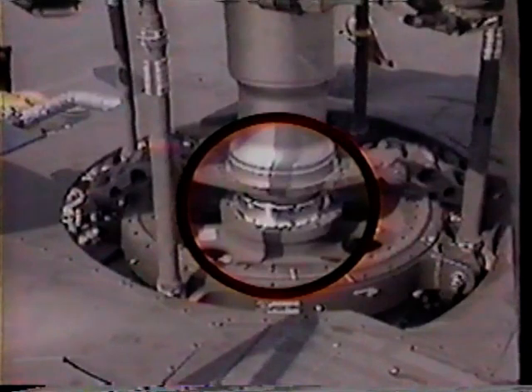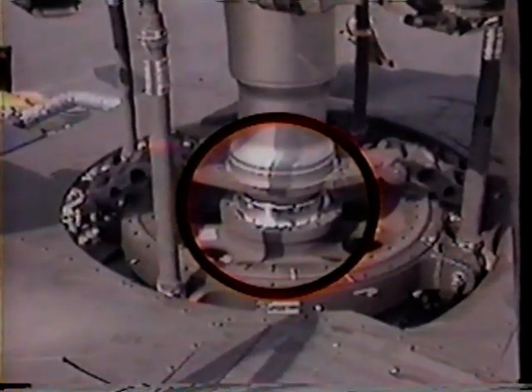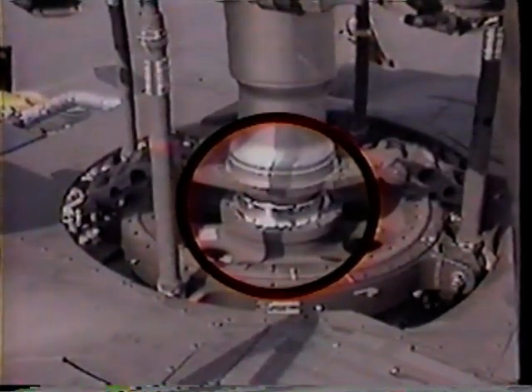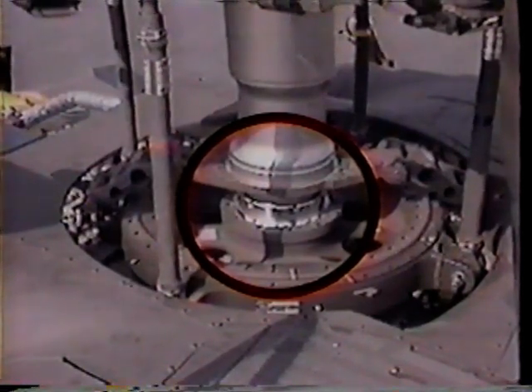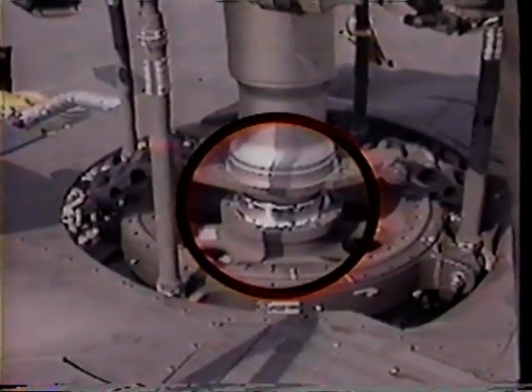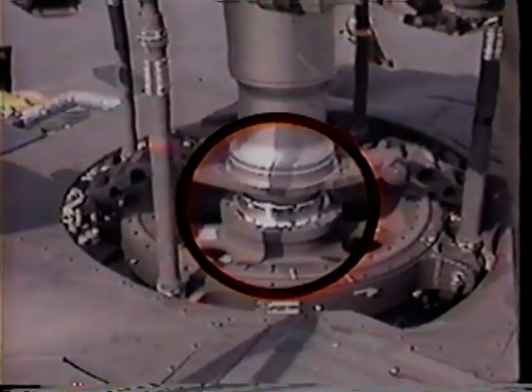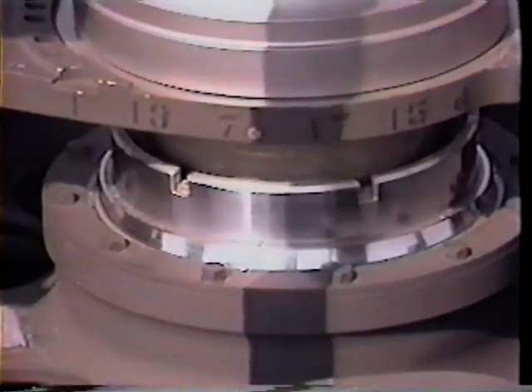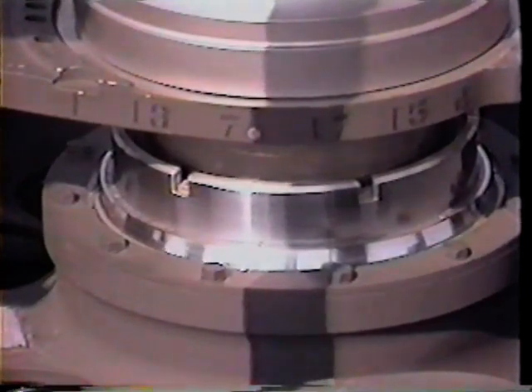The uniball is next. It's the bearing portion of the swashplate assembly located at the base of the main rotor shaft. It allows the fixed swashplate to tilt about the rotor shaft. Uniball components are made of aluminum and plated with chrome. Sometimes moisture gets under the chrome plating through a pit. This enables the galvanic effect to corrode the aluminum. When the aluminum corrodes, it causes the chrome plating to blister, crack, and flake off.